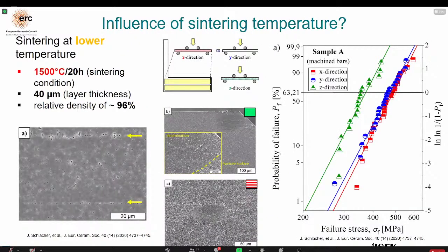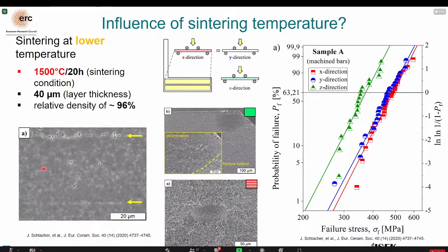So one sample set was sintered at lower temperature, and as you can see here, the microstructure looks rather fine-grained with a mean grain size of 1 micron. However, there is a higher level of porosity directly at interfaces. When we take a look at the strength distributions, we can see that the characteristic strength in X and Y direction is very similar, statistically not different, but the Z configuration is significantly lower. If we take a look at the fractured surface, it is observable that some kind of delaminations in Z direction occur directly at the interfaces. So you can imagine if the applied stress is perpendicular to this delamination, this will compromise the strength.